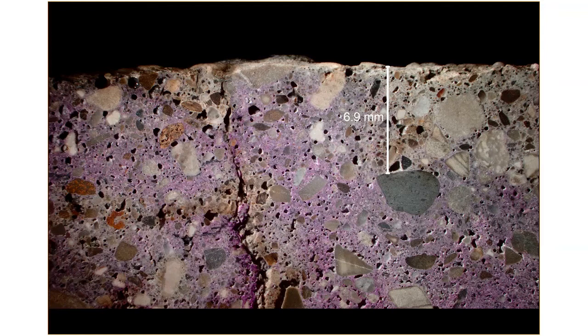We made a lot of great concrete prior to the 50s that was very dense. And another thing to note, which we'll see some pictures of, is that Portland cement was very coarse back then. Nowadays we like quick strengths, high early strengths, and the Portland cement is ground very fine. Back then, certainly at the time of Bellefontaine's concrete pavement, the Portland cement was ground as coarse as fine sand. And so we produced zero gaps in these concrete mixtures, from the coarse aggregate to the pea gravel to the sand to the Portland cement. These were very well graded mixtures through the Portland cement, and we made very dense concretes without even realizing it. So we have this evidence that we have low permeability.